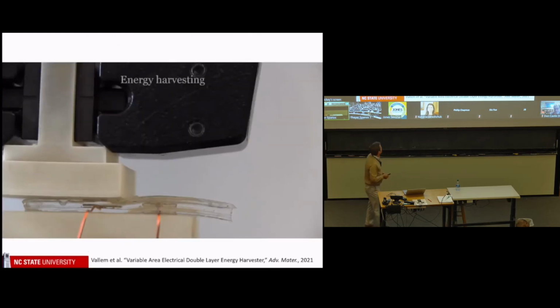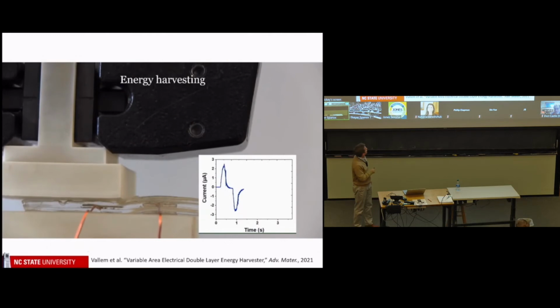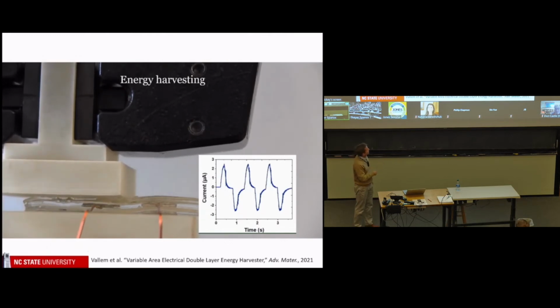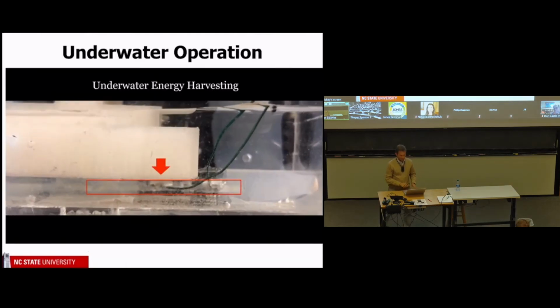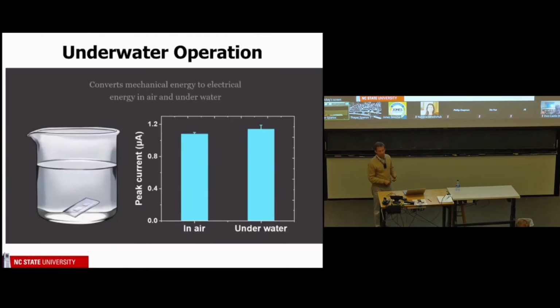Of course we've characterized it, and when you squish it, you change the area that causes charging, and when you let it go, it discharges. I'm showing you the highlights, but we went in and characterized the electrical double layer, did a circuit model, and showed that it behaves exactly as you would expect. And of course, hydrogel is basically water, so no surprise, it works underwater. That's interesting because you could put it, say, on the body, or maybe for ocean energy harvesting or something like that.